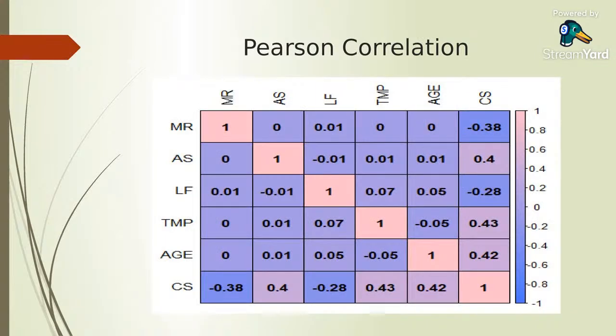Next, I performed a Pearson correlation. In the Pearson correlation, we can see that the effect of all the parameters on the compressive strength is high. For molar ratio, that is MR, it is -0.38. For alkaline solution, it is 0.4. For liquid to fly ash, it is -0.28. For temperature, it is 0.43. For age, it is 0.42. So you can see all the parameters affecting the compressive strength are very significant.